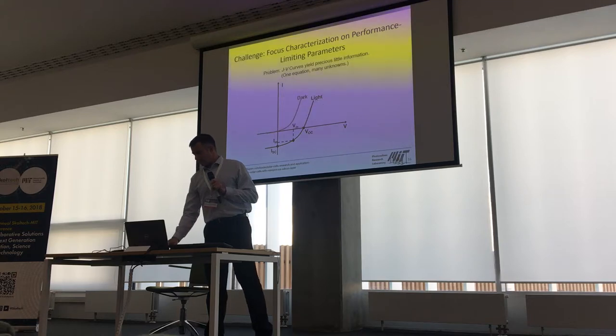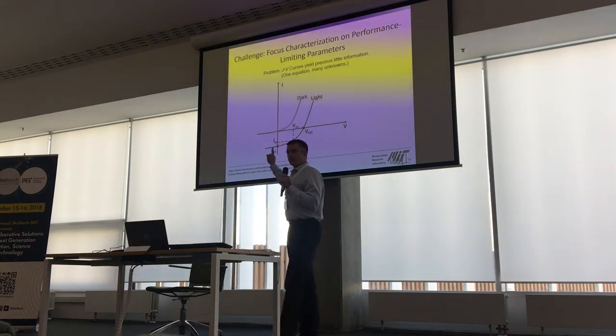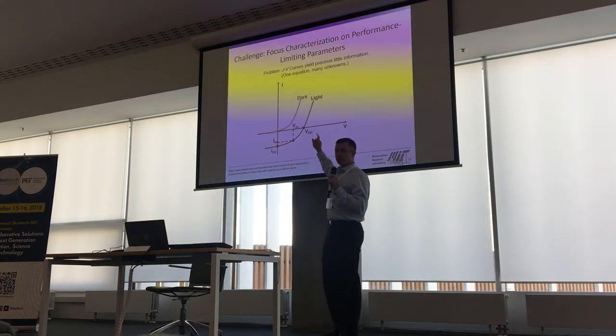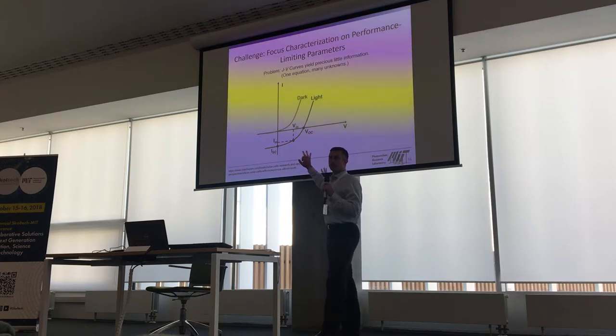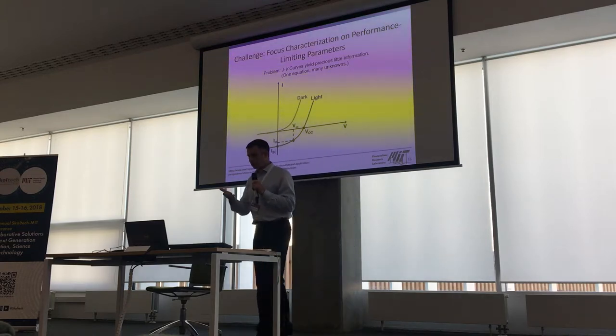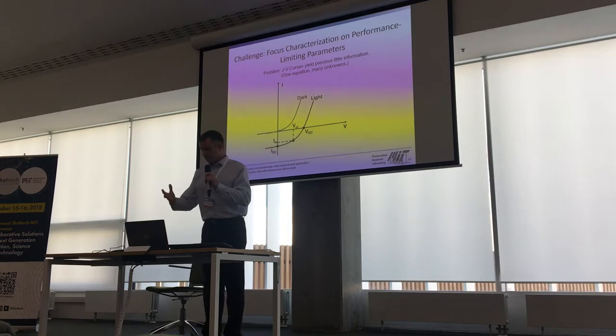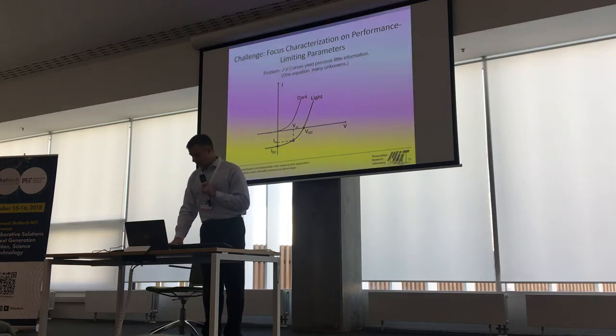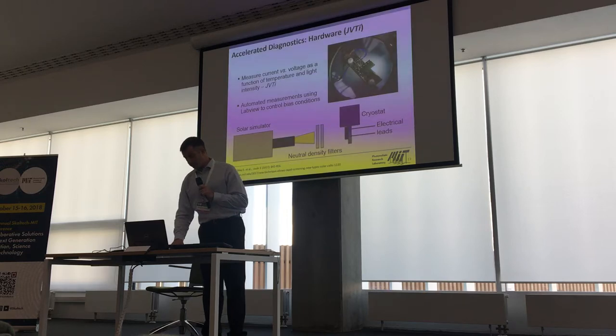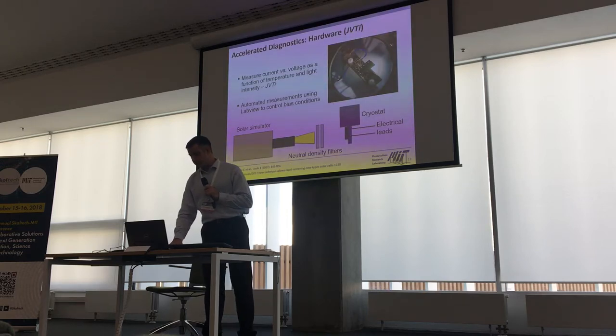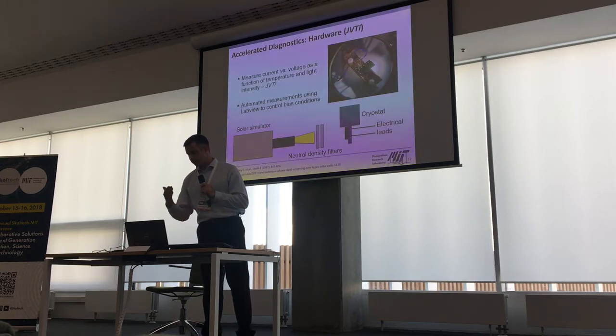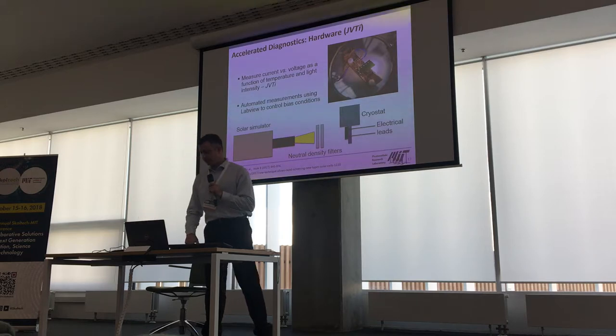We realized that information is embedded in every point along the current voltage curve, but typically we only look at 3 of them because we're limited by our cranial capacity to take many data points together and rectify them with a device model. But computers can do that well. So what we did is we developed a technique known as current as a function of voltage, temperature, and injection dependence.